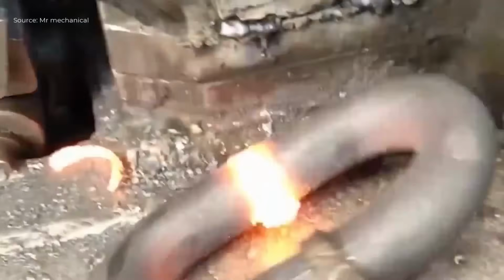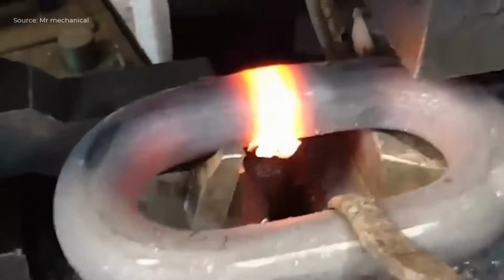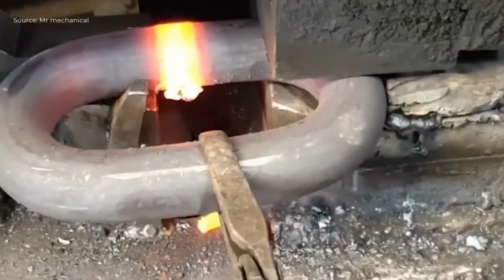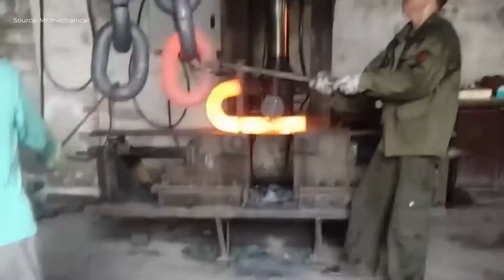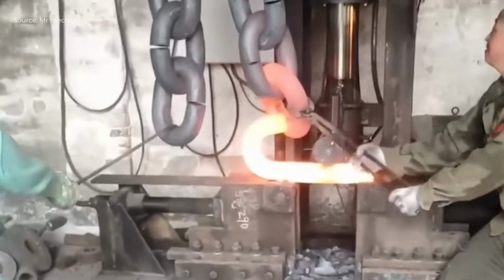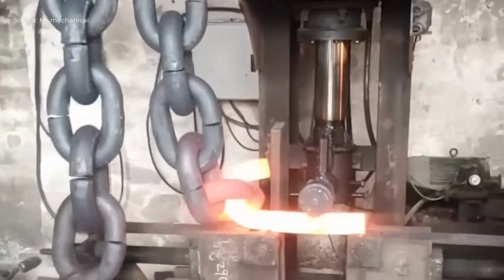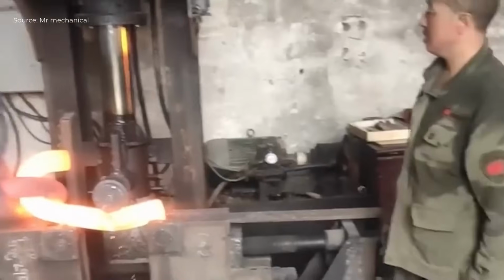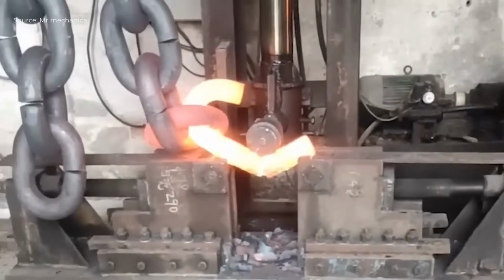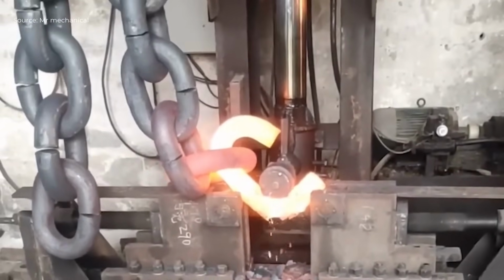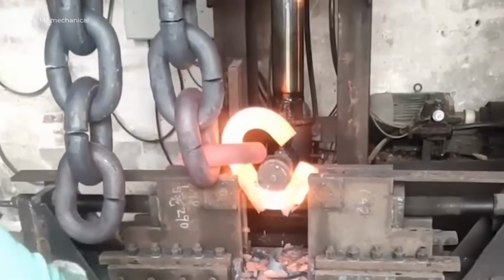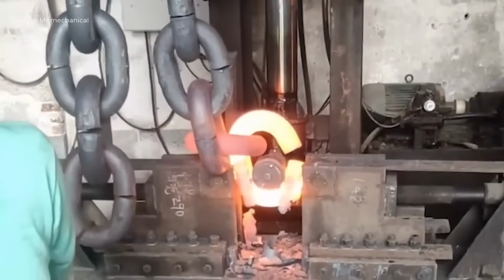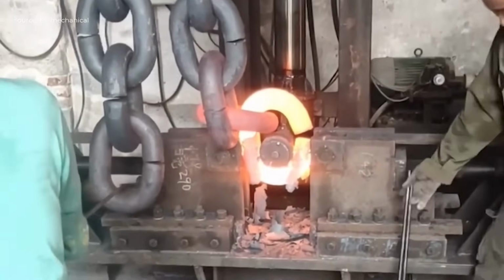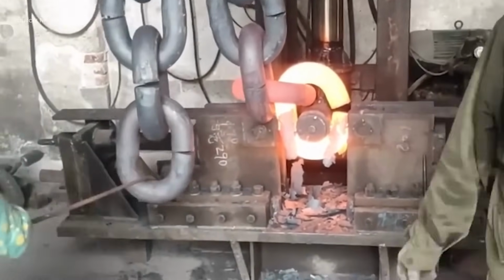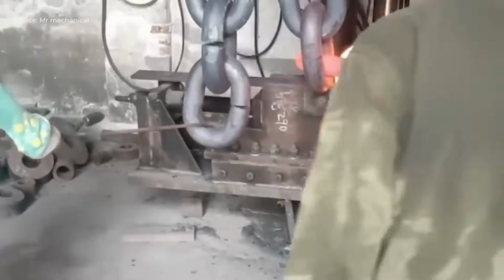The cut C-shaped components then move on to the machining stage, where their internal surfaces and contact areas are carefully shaped. Each component is equipped with a series of projections and corresponding recesses, which help align the two halves during assembly. The design also includes a projection that is slightly smaller than the clearance length on one half, allowing it to fit into the groove of the other half. On both sides of this projection, threaded screw holes are drilled to align with the through holes on the opposite half.